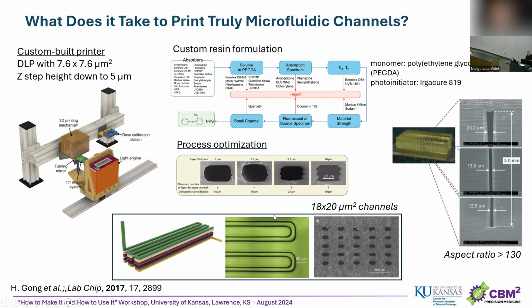And they optimized the process. You can see here the size of the channels, different channel sizes depending on your step resolution. You can see when each layer thickness was 5 microns, relatively nice and smooth walls over the entire channel, but when you increase it to 10 micrometers to build a 30 micron channel, you can clearly see each layer in the channel, right? After all these optimizations, they were able to demonstrate, for example, a serpentine channel with, I think, 18 by 20 micrometer channels and multiple different layers.